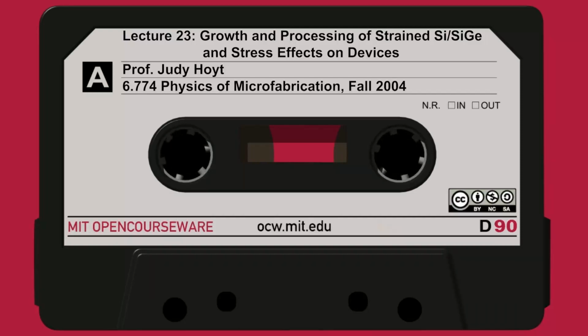For example, when you make a MOSFET, you don't just make an individual MOSFET on a device. All around the MOSFET, we do something called shallow trench isolation that we talked about in this course. We dig out a trench all the way around the MOSFET, and we fill it up with oxide or some insulator. Well, IBM showed back in '97 that, depending on how you fill that up, you can potentially induce stress, either compressive or tensile, depending on what material you put in, because you're digging a moat around the device and putting some material in it. So you can actually use the STI, so-called, to induce stress.